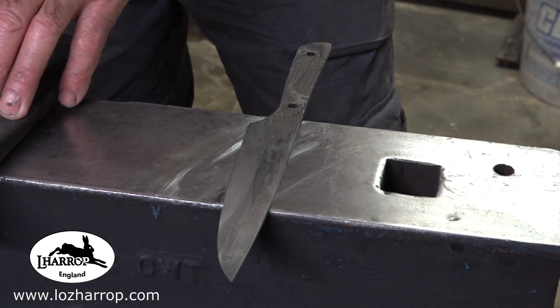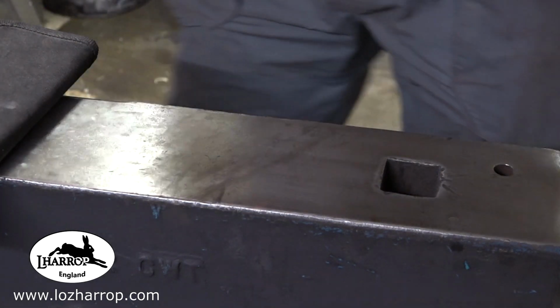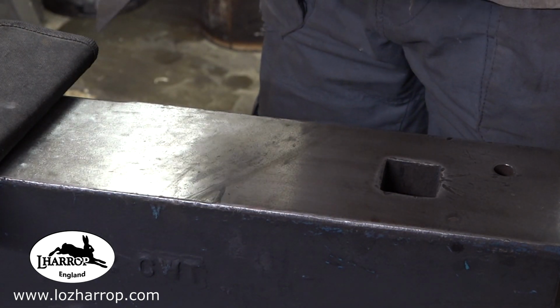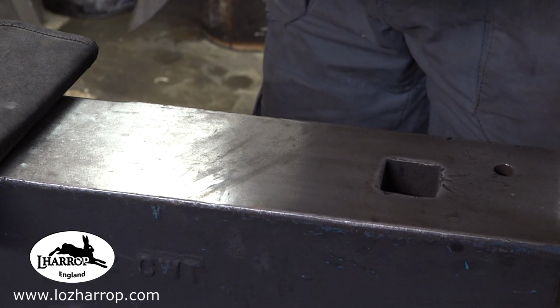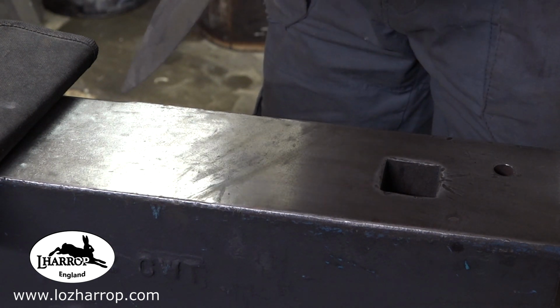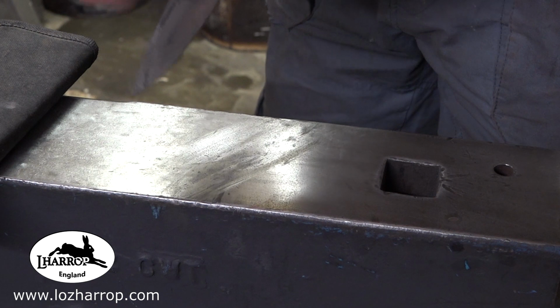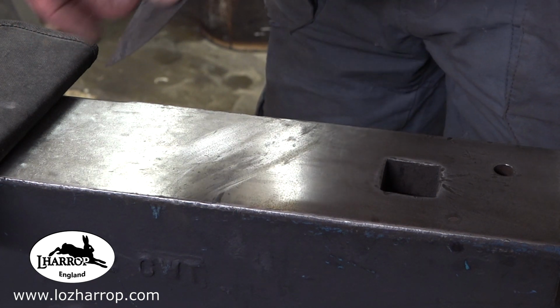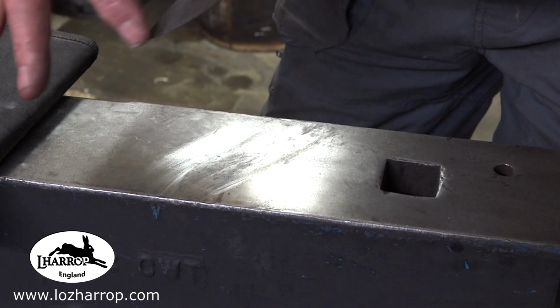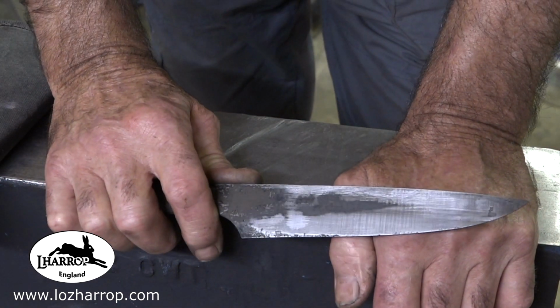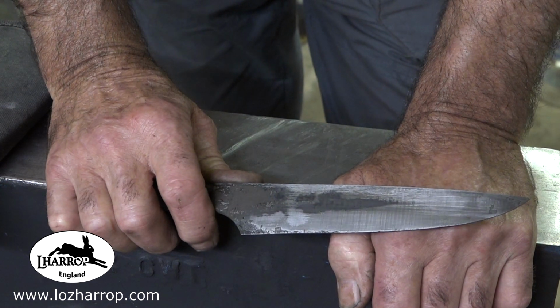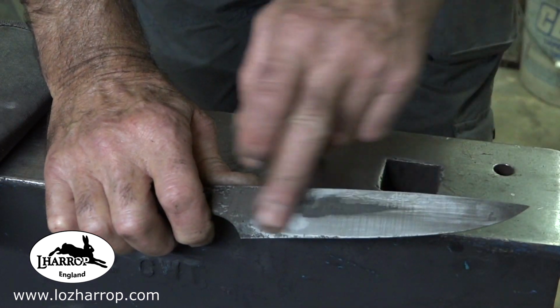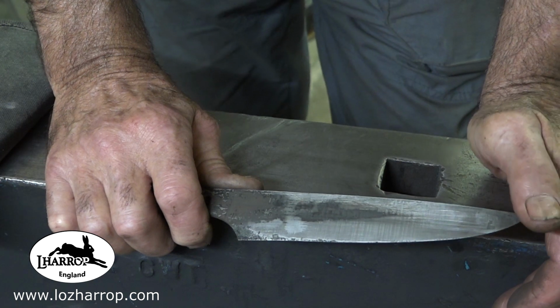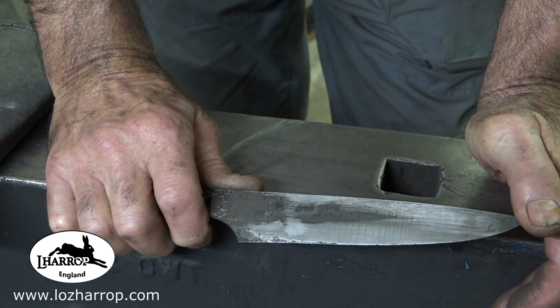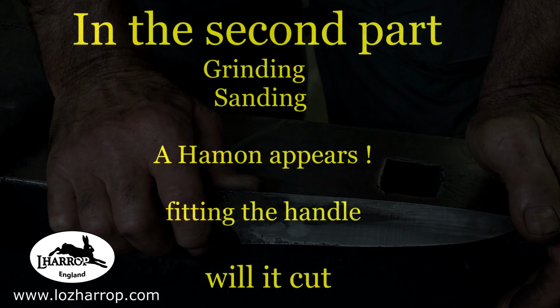Right, I need to temper this now, because that edge could crack at any point. It is so hard. The stresses in that steel between that softer back and the harder edge, a lot of stress and tension in there now. And all I'm going to do is knock the temper back a little bit, because I want the edge 62, 63 Rockwell anyway. So I'm going to take it to 120, 130 degrees for an hour, 2 hours.